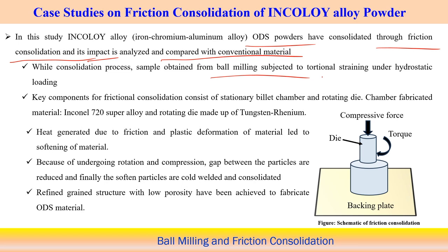So in this consolidation process, first we obtain the sample from ball milling. We create the sample from the ball milling operation and subject it to torsional straining under hydrostatic loading. Torsion means we apply torque, and along with the compressive force, that means with the application of hydrostatic stress, the powders are basically interacted between these two elements.